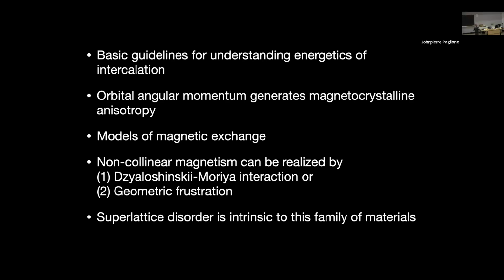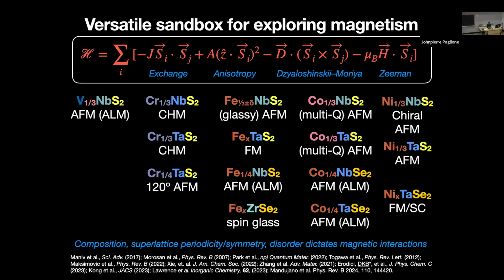Oh, I think there are lots of reasons to study all of them. In our case, at least what we've published so far is only on the sulfides, but there's been a lot of work also on the selenides. This is one example from Efrain's group on the cobalt 1/4 tantalum selenide. I think there's a niobium analog as well. And this nickel system is pretty interesting. It goes between superconductivity and ferromagnetism, depending on the amount of nickel. So I think the selenides are very interesting as well.